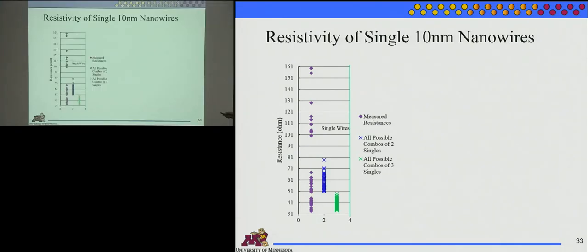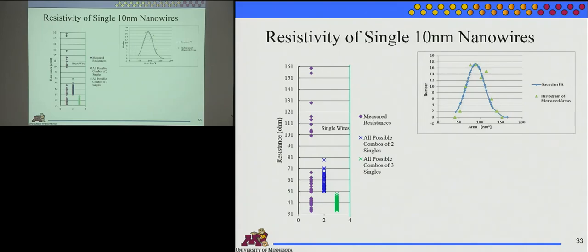But it's parallel resistances, you should get half, right? If you measure 1 wire, you get a value. You measure 2, you should get half that value. And we never see a measurement around 80 for all of the different measurements we took. We actually had more down under here that are not as significant. All right, so we said, okay, what if these are single, and these are just small wires because our areas have a Gaussian distribution? So if we have small wires, they'll be more resistive. Big wires will be less resistive. But it's not very Gaussian looking.